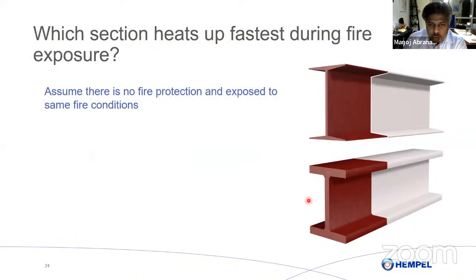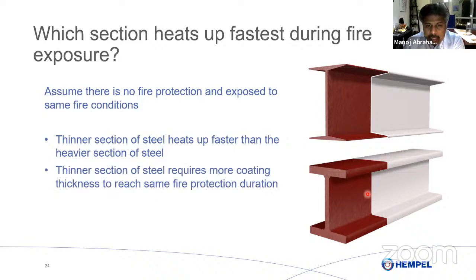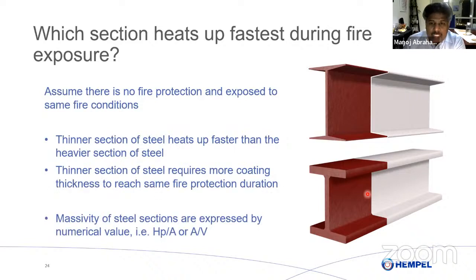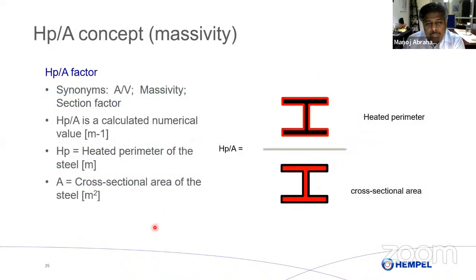So when we look at these two steel sections, one is thin, another one is thick. At the time of fire, what we know is the thinner section will heat up faster than the thicker section. So I need to protect the thinner section with more paint, while the thicker section can receive a lesser coating thickness. We call this the section factor or massivity of steel. So for thinner sections and thicker sections, we design something called HP by A. It's primarily the heated perimeter.